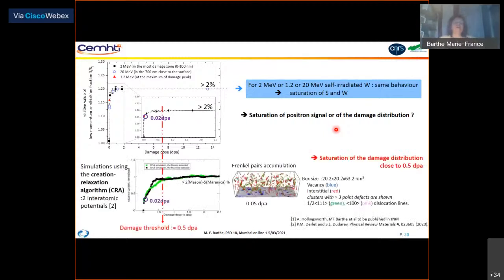And if we compare this data with some calculation using the creation relaxation algorithm, it corresponds to Frenkel pair accumulation in the boxes, and look at what type of defects still exist after different damage dose. And we can see that there is also saturation in this calculation with a concentration of vacancy that is about 2 or 5%, depending on the empirical potential which is used in this calculation. And it is close to the number that we obtain with positrons.